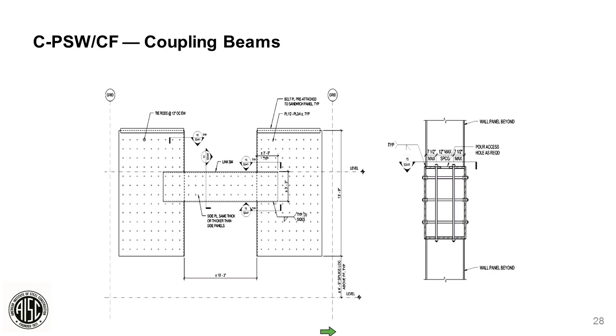If we look at coupling beams, we extrapolated that same methodology. Coupling beams are essentially built-up box-shaped elements, tubes, that are infilled with concrete. In this case, in addition to the infill of concrete, we also put cross ties both directions again. What research, we'll talk at the end about research, would show that you probably don't need any of those cross ties through that section provided you meet certain slenderness ratios. But again, with Rainier Square, given the limited research that was available at the time, we chose to be very conservative on this approach and provide additional confinement in the coupling beam elements as well.